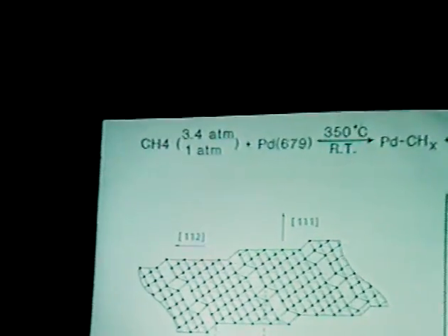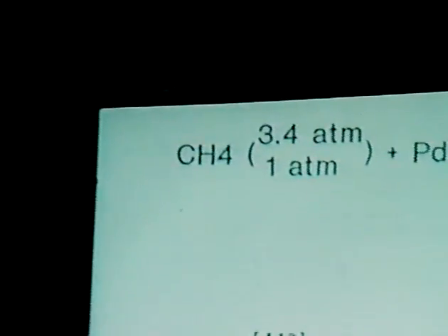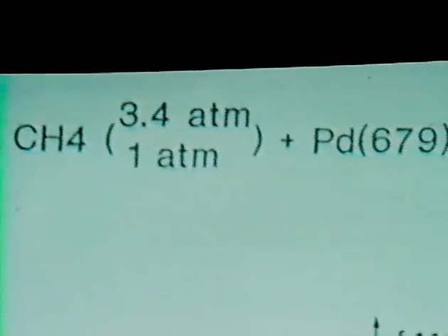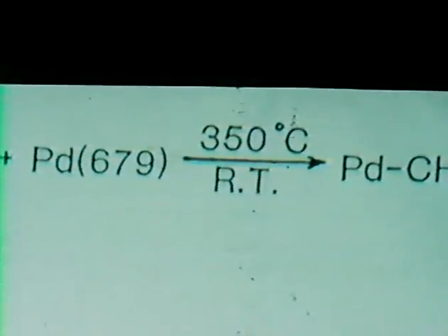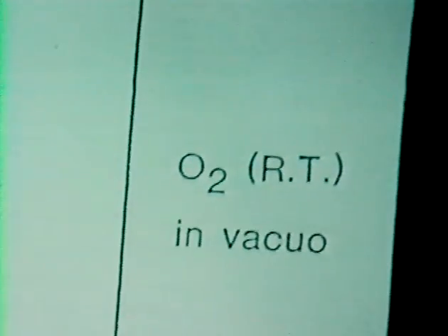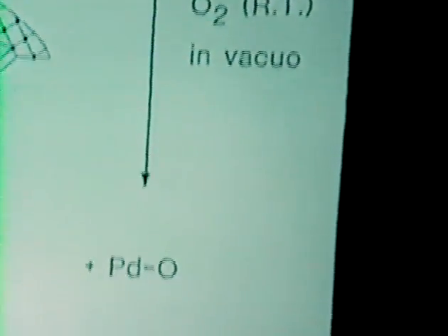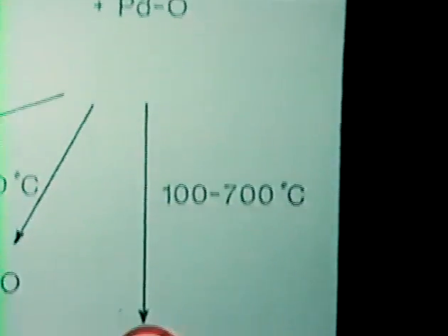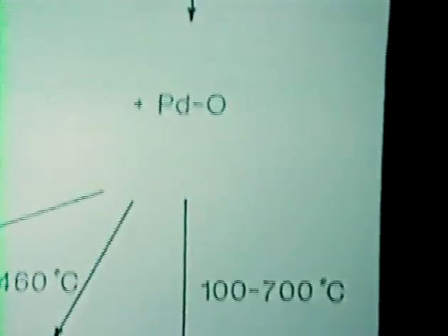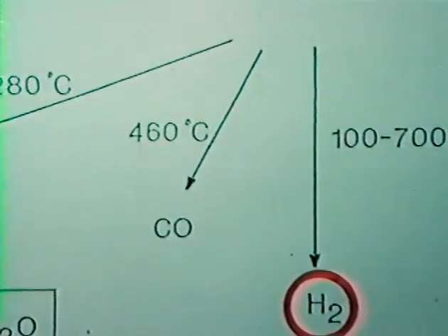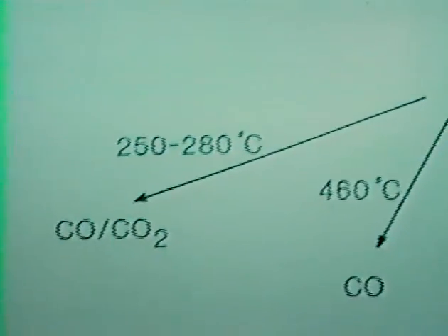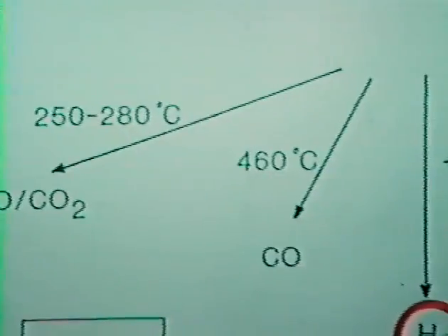Now, the next principle of attack of methane is even simpler. It's the dissociative chemisorption of methane on metals. But if you want to oxidize the fragments, you need to use a metal which is not non-noble. Because if you use a non-noble metal, by the time you bring in oxygen into the system, it is going to be converted to an oxide and you don't have a metal catalysis. Take titanium and you bring a little bit of oxygen, you convert titanium to titanium dioxide. So the key is to use a metal that cracks the carbon-hydrogen bond and yet dissociatively activates oxygen, but it's also able to release oxygen.